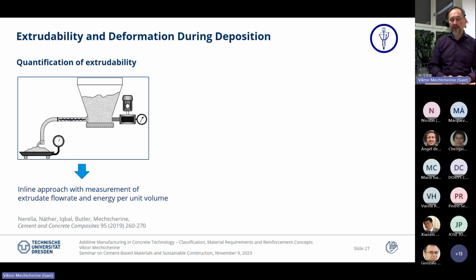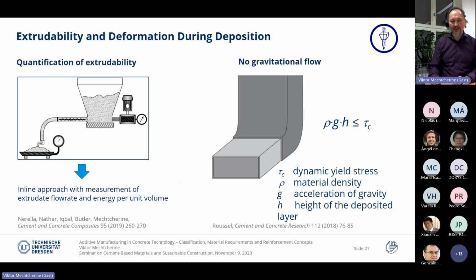Then extrudability as such. First we are interested in the quantity of the material which is delivered, and the best way to measure it is really just to print some material, not to produce any kind of structure, but rather to print it on a scale, and then you have the quantity of the material per time which is delivered. Of course, you can also measure geometry, and assuming some specific weight of the material, you can come to the same result.